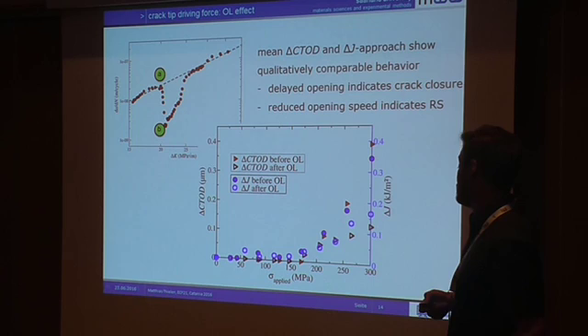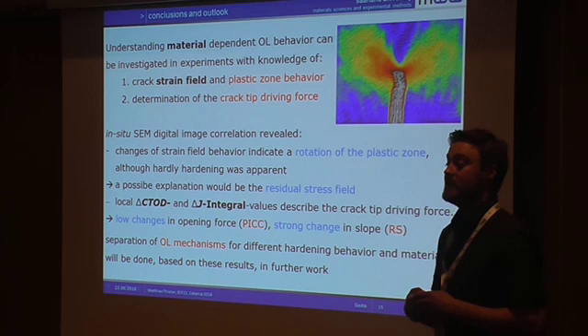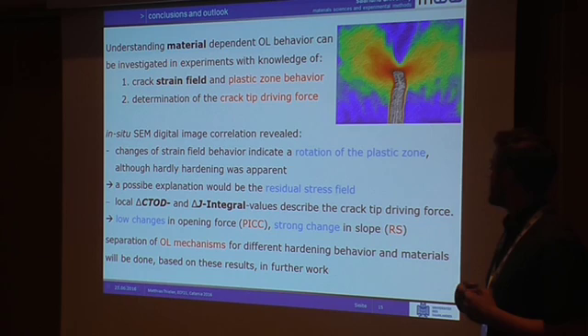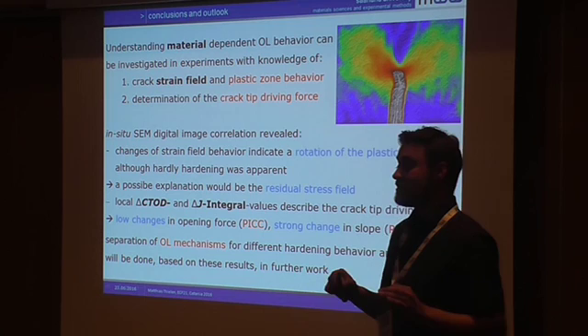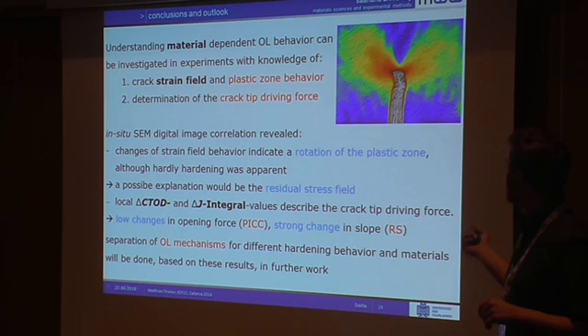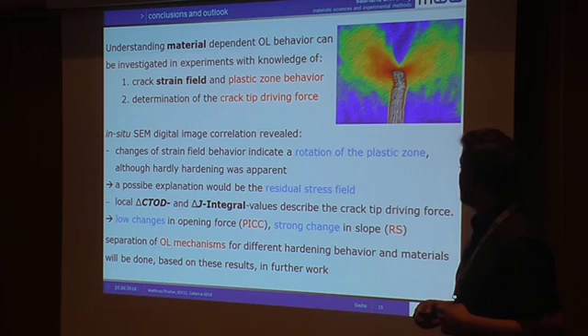To conclude: we showed what we need to describe material behavior regarding the overload effect — the hardening behavior, the plastic zone behavior, and the crack driving force. We demonstrated that with SEM digital image correlation using the plastic zone, delta-CTOD, and delta-J, we found small changes in the crack opening point but large changes in the slope, indicating a strong dominance of residual stress in this case. We would have liked to show results from another material, but our SEM was broken for two months. Here is our first result for a strong strain-hardening material before the overload, and you can already see that the plastic zone looks very different from the non-hardening material. Future work will check these mechanisms for several materials to verify if what is shown in simulation holds in real materials as well. Thank you for your attention.